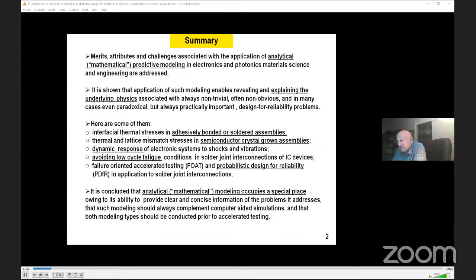I'll particularly cover 5 items, which are the interfacial thermal stresses. Everything is analytical mathematical modeling. Thermal lattice mismatch stresses and their interaction. Dynamic response of electronic systems to shocks and vibrations. Avoiding low cycle fatigue conditions. What could possibly be done to do that? And if all the measures are not successful, at least the size of the inelastic zone will be minimized. And that will certainly improve the long-term reliability.